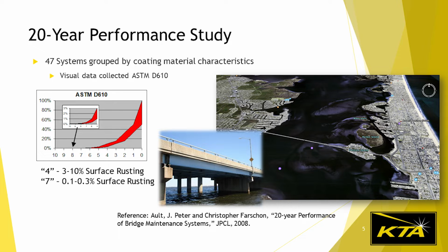In 1986 and 1987, the New Jersey DOT applied 47 different coating systems to individual spans of the eastbound Mathis Bridge. Each system was applied to a complete span of approximately 4,000 square feet. The DOT wanted to know how these different systems were going to perform over time. 18 different coating manufacturers donated coating systems for this experimental project, and 17 of the 18 manufacturers had a rep on site to ensure that their product was being applied per requirements. Systems range from metallizing, various zinc-based systems, epoxies, aluminum epoxy urethanes, vinyls, and oleoalkyds. They were applied to varying levels of surface prep that range from an SP2 to an SP5.